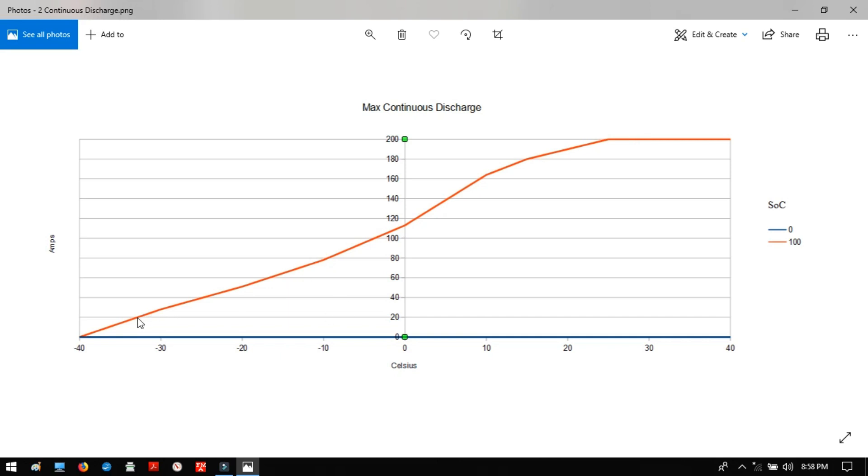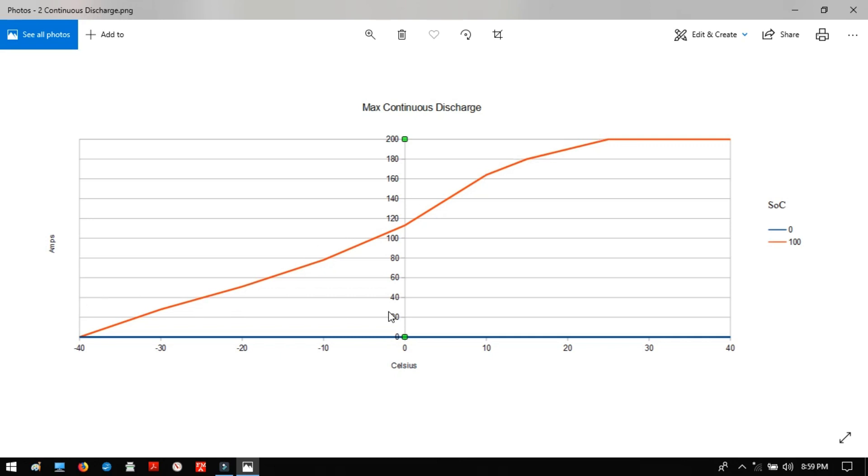So by zero, I'm down here to about 110. And then by minus 20, I'm down to about 50 and so forth. This down here at minus 25 degrees Celsius is close to 40 amps. So that 40 amp discharge is roughly as hard, as much wear and tear on the battery as 200 amps when it's 25 degrees Celsius up here. So you can insulate your battery, you can heat it, you can cool it, whatever you need to do, or use electronics or manually restrict it, or just deal with the fact that your application is going to be in whatever temperature range you're going to be using it.